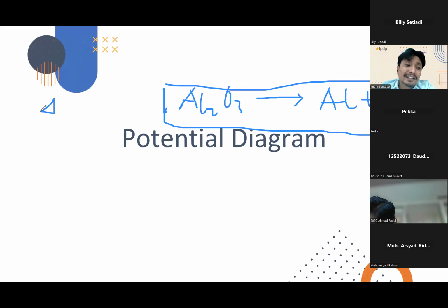For this reaction, the delta G is positive. You can check in the Ellingham diagram. The reaction to the left side is negative, then the opposite reaction is positive. The Ellingham diagram is for reactions of formation. If the reaction of formation is negative, then the opposite, the reaction of decomposition, is positive. Then the Gibbs energy is positive.